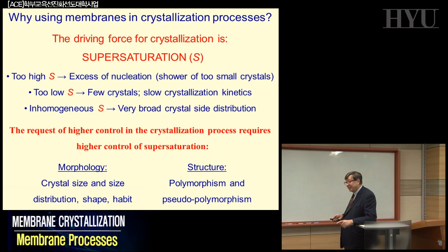Where is the interest for membranes in crystallization? The driving force for the crystallization process is to create supersaturation, to create this step in which you start to create what is called a nucleus, and from the nucleus you then grow your crystals. And that is happening in this step of the supersaturation of your solution. If you don't control supersaturation in the right way, you can have some negative aspects or some positive aspects. For example, when you have too high supersaturation, you have an excess of nucleation. That means you have a shower of very small crystals. If you have a low supersaturation, you have very few crystals and very slow crystallization kinetics. The growth of the crystal is basically quite low.